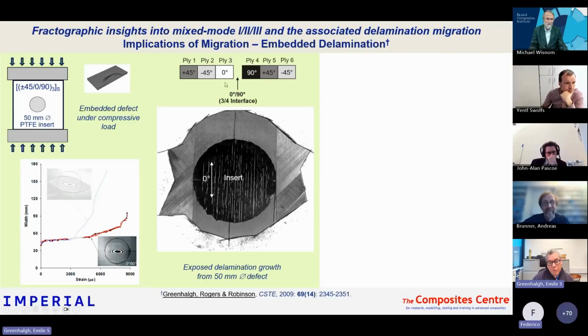And it was just that when the delamination is between the fifth and sixth ply, it jumps up an interface into the interface where the 90 ply is the upper ply, and in that instance the 90 is in the direction the delamination wants to grow, which is transverse. So this is why it rapidly grows across, and you only get up to about 6,000 microstrain. But in the 0/90, it jumps up through the upper plies and never gets into an interface where the 90 is dictating the growth, leading to this very convoluted process, which leads to a very sluggish damage growth. But everything else, the samples were identical.